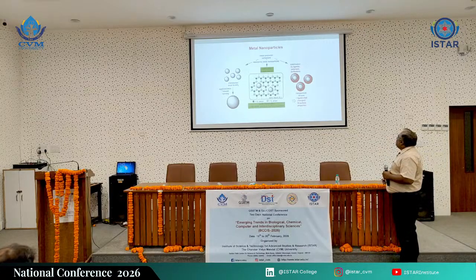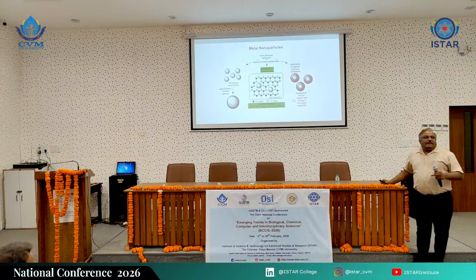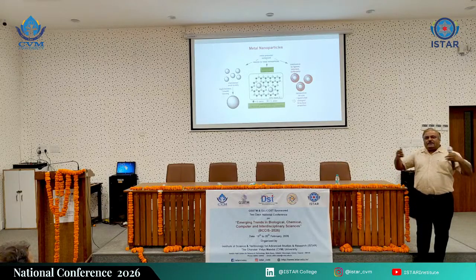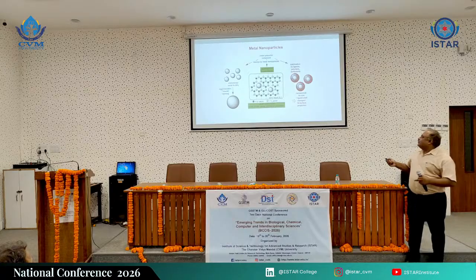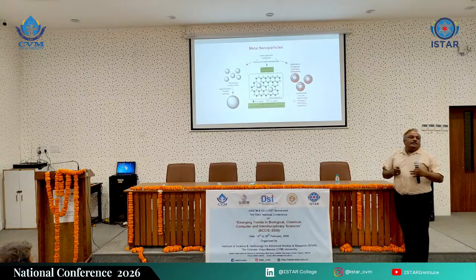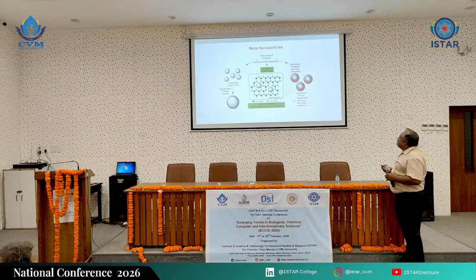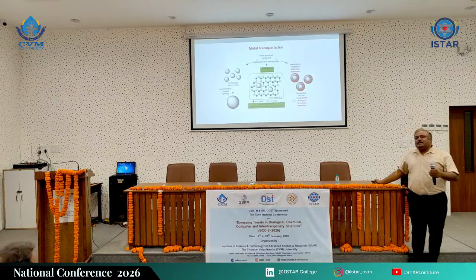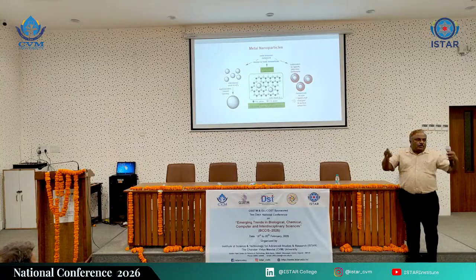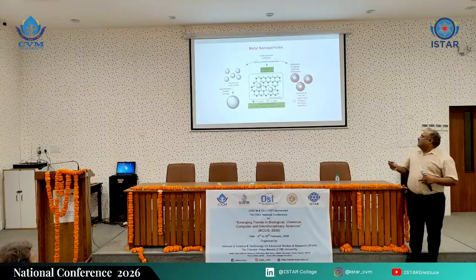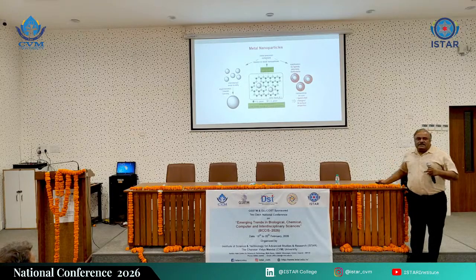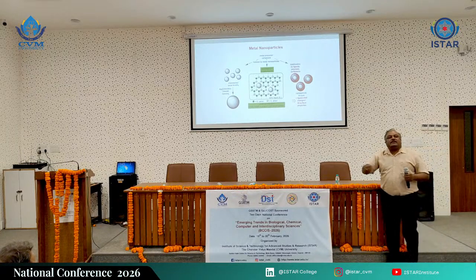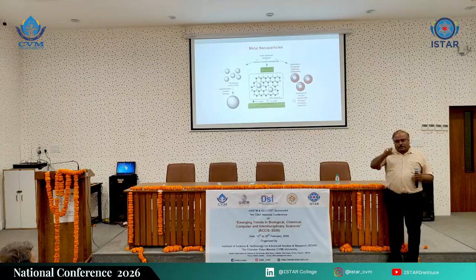Yes, many times these coatings are in situ, and they are labile. Many times they fall apart and again form, fall apart and again form. During that process, if they get enough time, they may start agglomerating. So that optimization needs to be carried out, which type of surfactant you are using and how quickly it is forming a kind of coating on your metal oxide or metal nanoparticle surfaces. And another approach is, once you synthesize nanoparticles, to permanently coat a certain type of nano coating, which will not allow them to bind again.